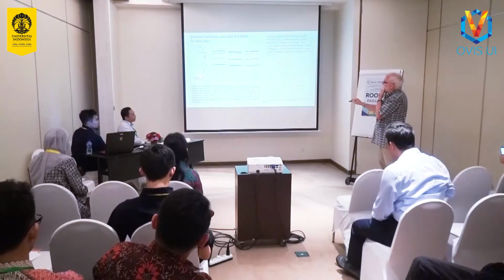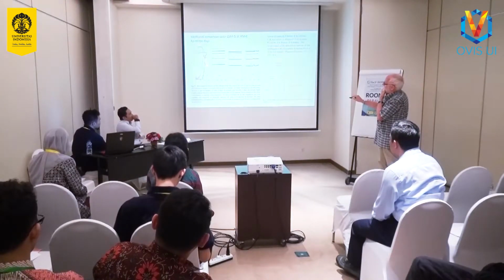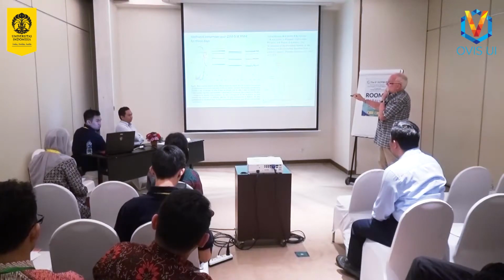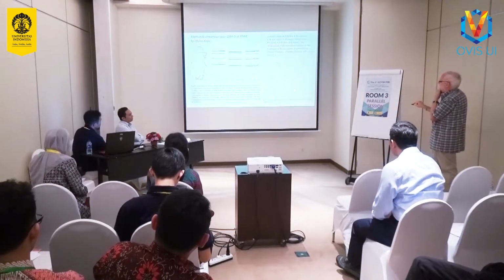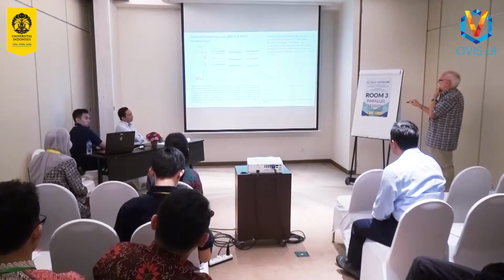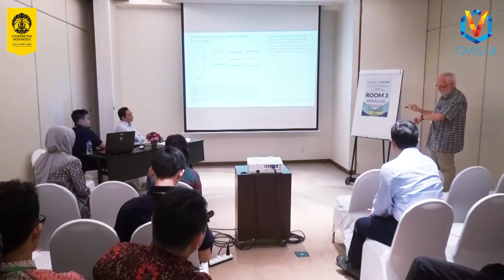Initially, there's an induction period. You see initially there's dimethyl ether coming out first and then going down, propylene coming up, and then aromatics forming. This is the initial stage. And here's the liquid products that we catch and analyze offline, and they're a mixture of benzenes, methylbenzene, trimethylbenzene, tetramethylbenzene, and substituted naphthalenes.